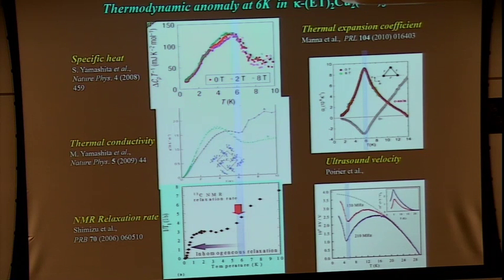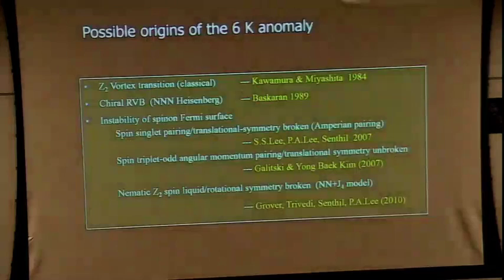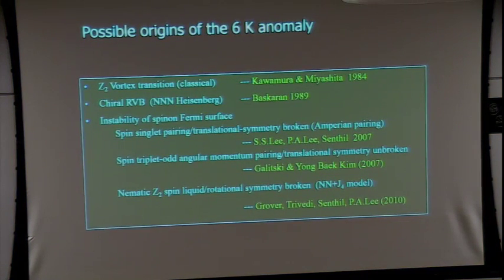And this nature of the transition is broad in other materials. You can see this NMR anomaly is not a clear anomaly, it's some crossover from here to here. And also the ultrasonic velocity shows some softening of the lattice around 6 Kelvin. So something happens around 6 Kelvin. And the origin of this anomaly is completely open.